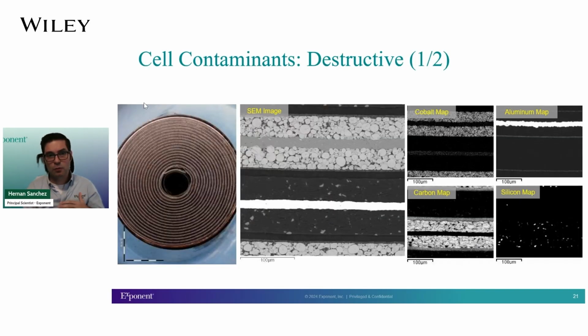So one of the things that we usually do when approaching one of these is to use the CT so we have a good sense of where it is located on the cell, and then we can do cross-sectioning and then polish towards finding the feature of interest. This is a slightly different example in which, when we were doing a cross-section analysis, we found silicon on the negative material, which many cells have in their formulation, but sometimes it happens that when a cell manufacturer changes from one batch to another, if the batches are not properly cleaned, you might end up with silicon on a cell that was not designed to have it.